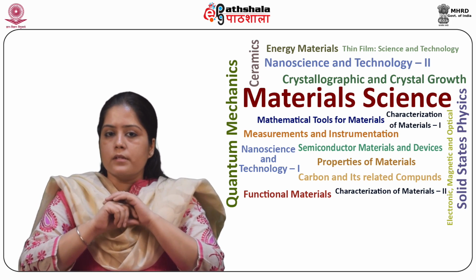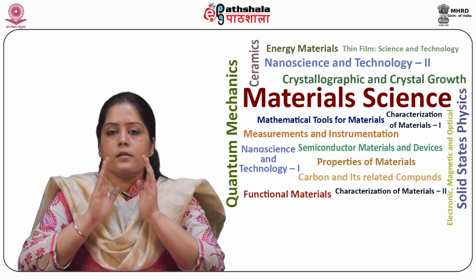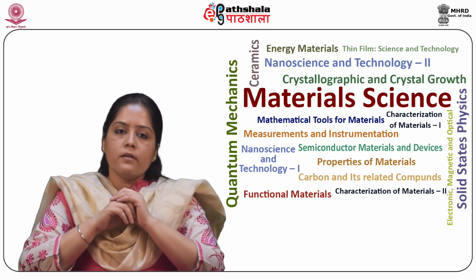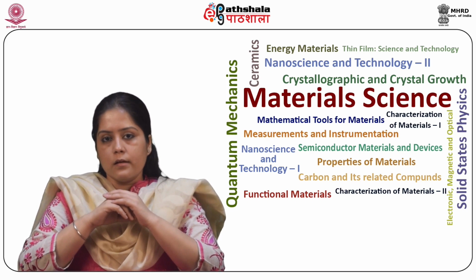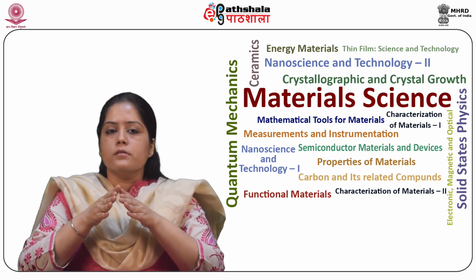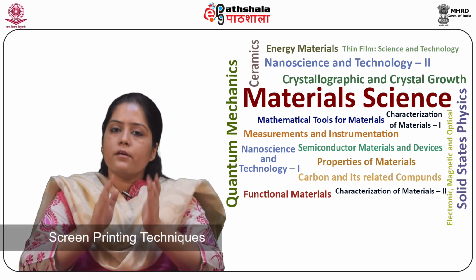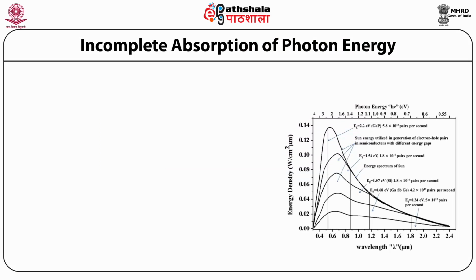Grid line widths up to 20 microns are possible using evaporation through the photolithographic technique, and up to 50 microns using screen printing techniques.